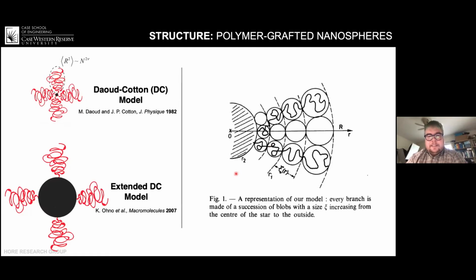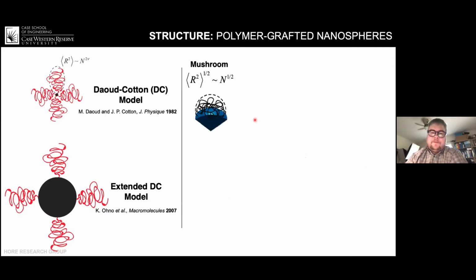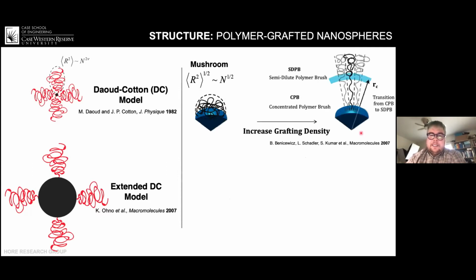So you can see in this schematic from the original paper in 1982 that you can represent the core in a way that looks like a nanoparticle, and you can see that the polymer is stretched locally and becomes more relaxed as you move farther away. Now, specifically what that means for a nanoparticle is that if you have a low grafting density, you're just going to have an ideal chain that kind of is tethered to the surface of the nanoparticle. But as you increase the grafting density, you get 2 regions.